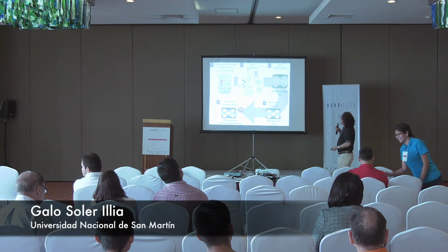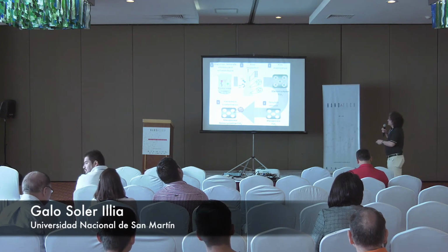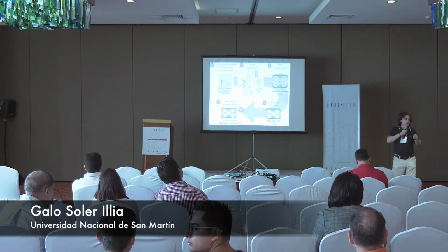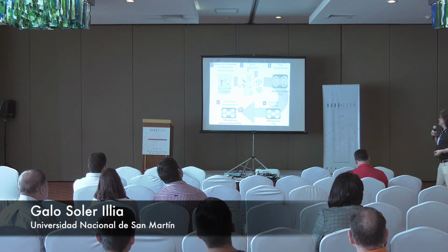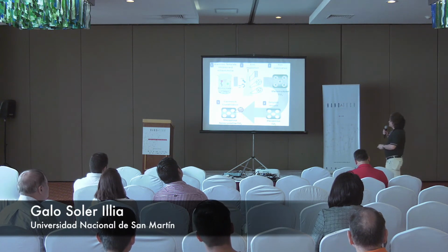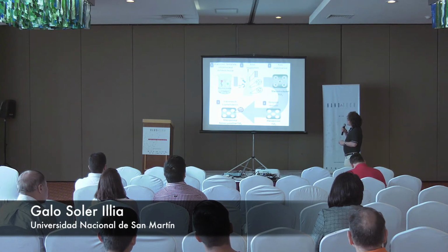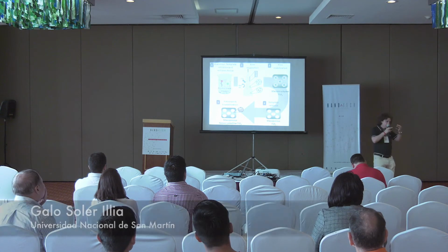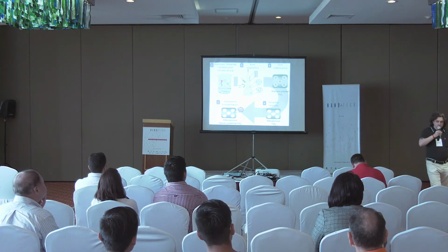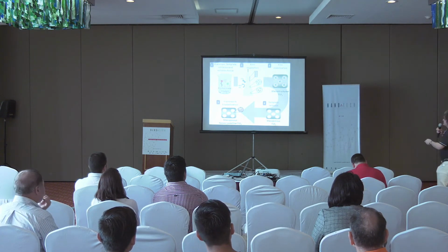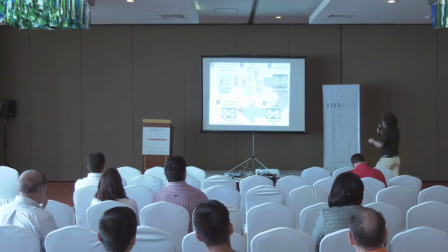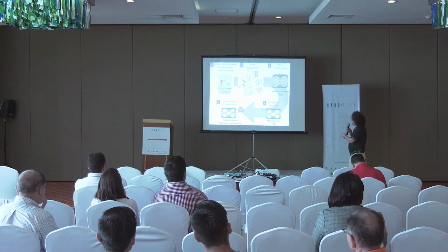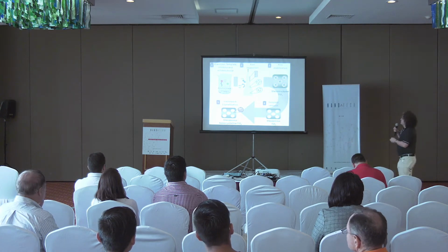So, how do we make these materials? We have this magic solution. It takes a couple of months to be trained in how to prepare the solution with an organic volatile solvent like alcohol, a little water, the inorganic precursor, the core template, mix everything like a good chemist. Then you deposit a thin film either by dip or spin coating. I will tell you then the process of film formation.